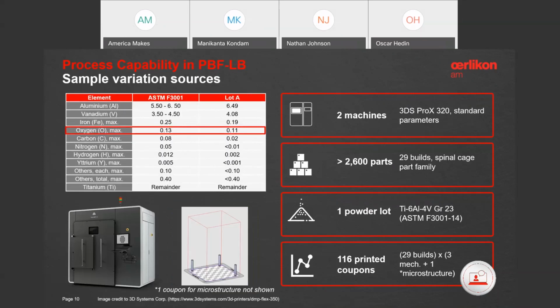Thank you, Oscar. So similarly for laser beam, we used 2 3D Systems ProX 320 machines for the study. We analyzed 2,600 parts across 29 builds, and all the parts belong to one single cage family. The powder lot used in the study is a titanium 6-4 grade 23 to ASTM F3001-14. The table on the left-hand side of the screen shows the chemical composition of the powder lot used.